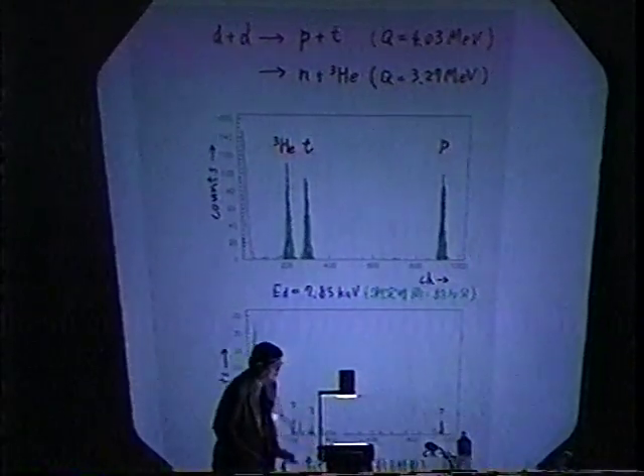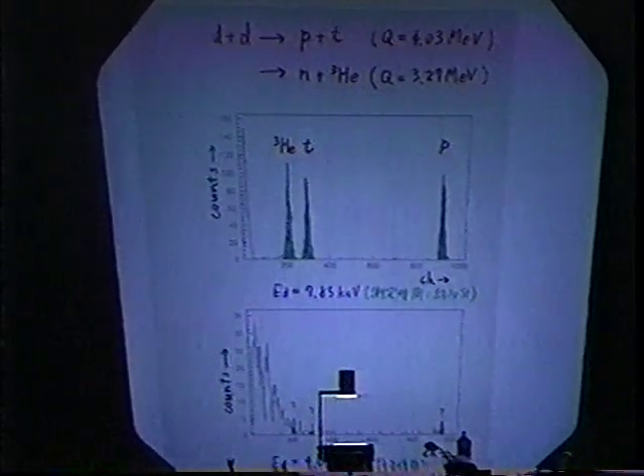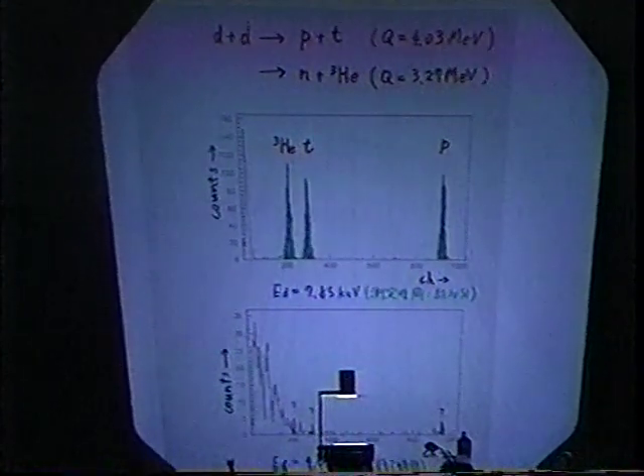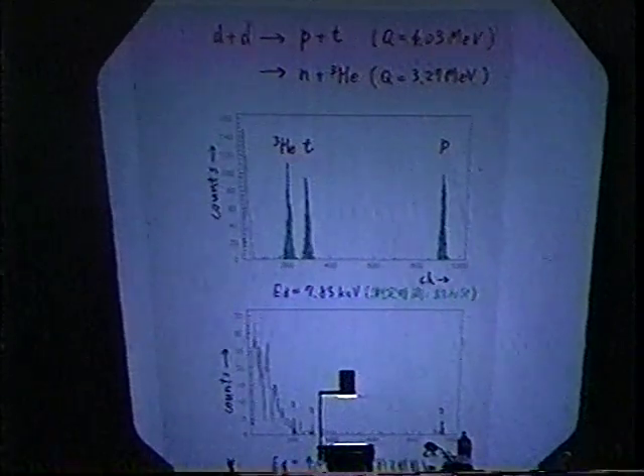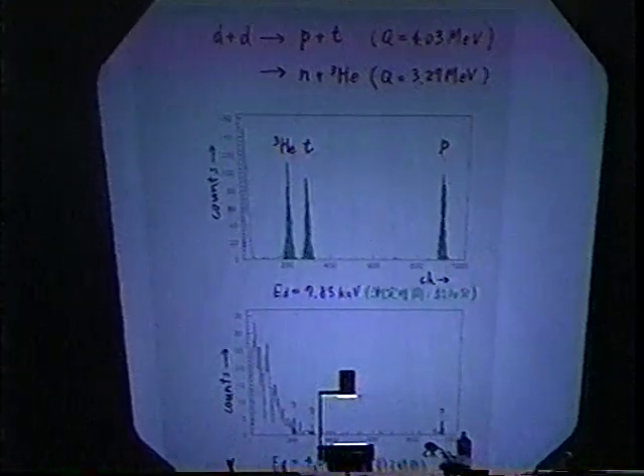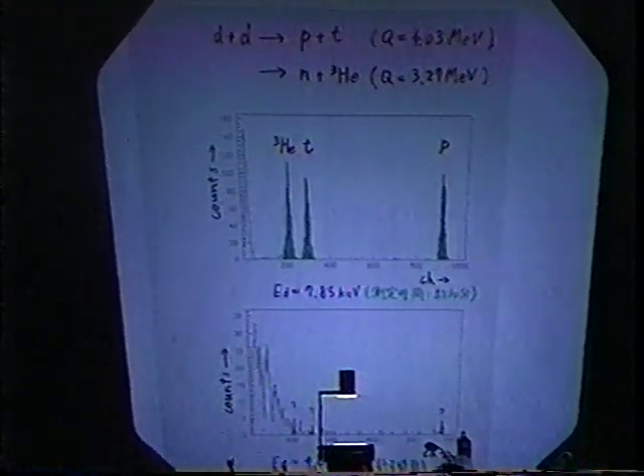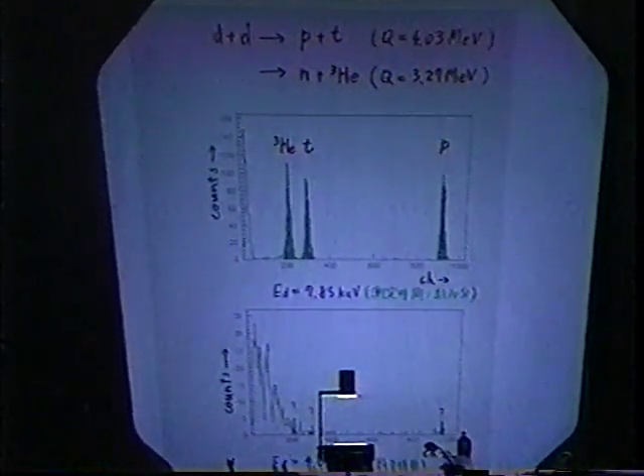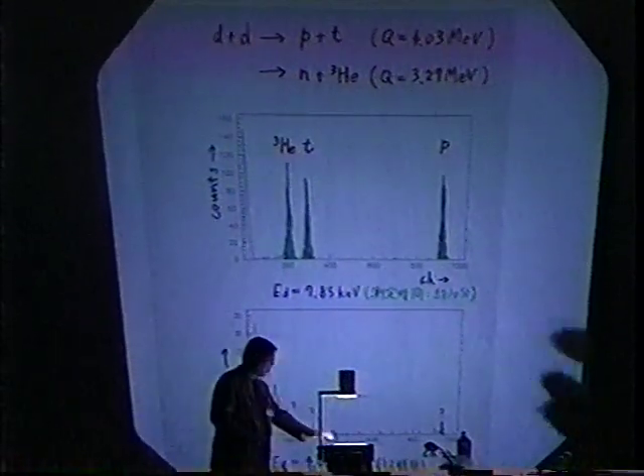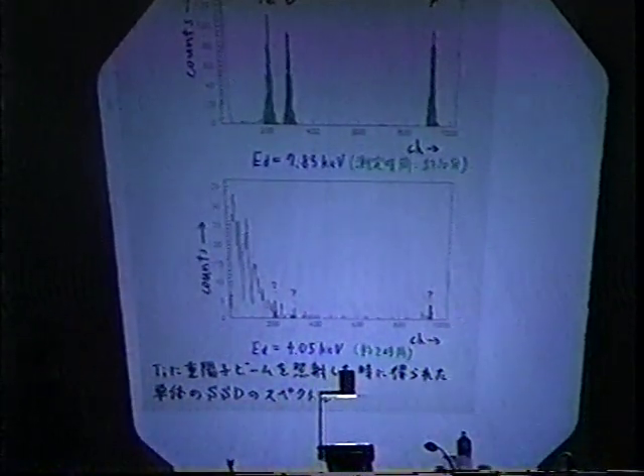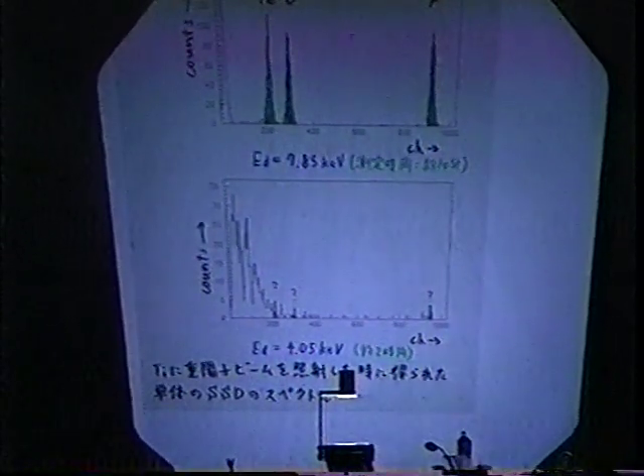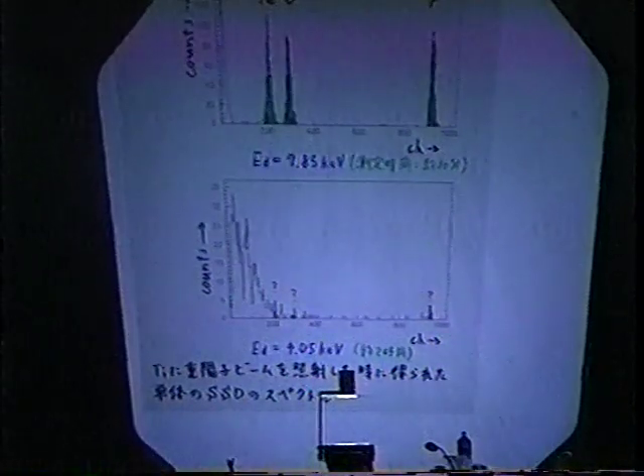If we measure with just a single counter, we can get this kind of spectrum. This is the proton from this channel, this is the triton from this channel, and this is helium-3 from this channel. In this case, the measurement time is very short, so fortunately we don't have so many electric noises. But if we lower the energy, let's say down to 4 keV, then we need time to accumulate the events. Therefore, sometimes electric noise destroys our spectra. But anyway, we did some single measurements.